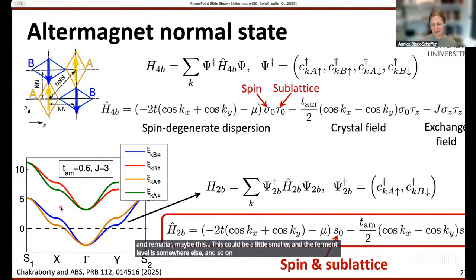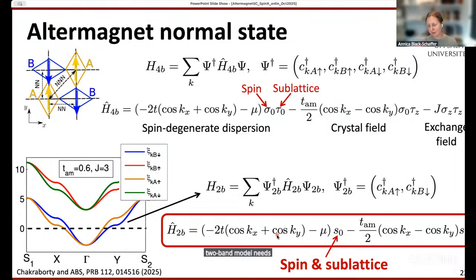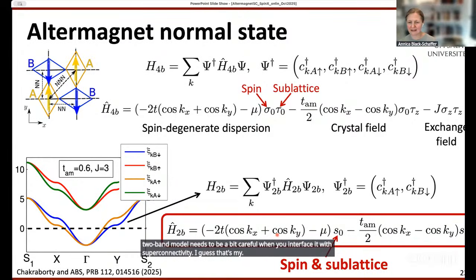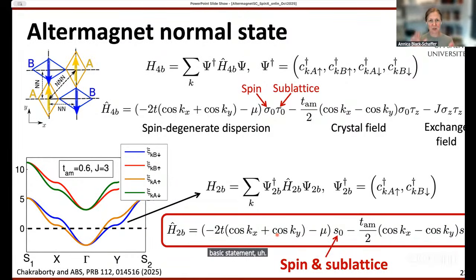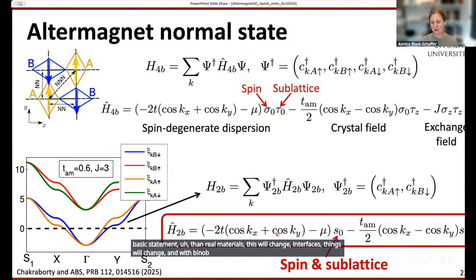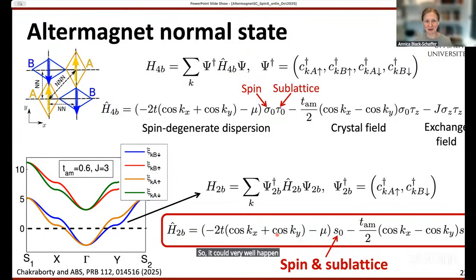So it will depend. But at the simplistic level, if you are thinking of altermagnets with a two-band model, one needs to be a bit careful when you interface it with superconductivity. That's my basic statement. In real materials, with interfaces, things will change. And with spin-orbit coupling, you can obviously go from a spin singlet to a spin triplet state and so on. So it could very well happen, I guess, is the short answer.